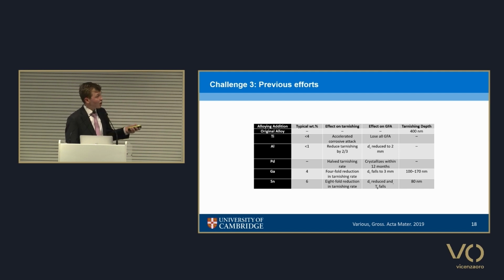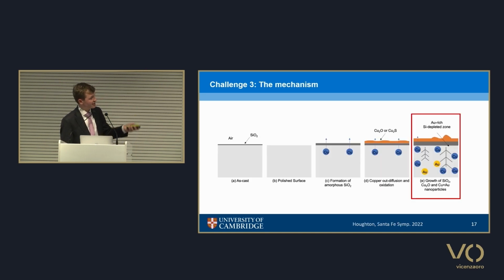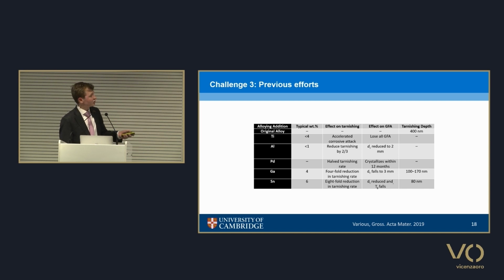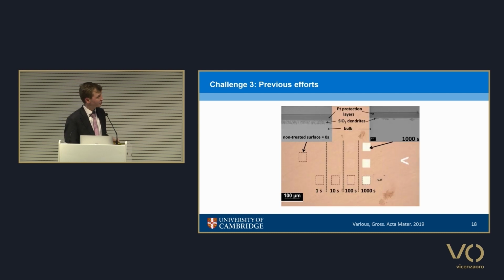People have tried to add other elements in order to try and stop the tarnishing behavior. And in general, we see some improvement in tarnishing behavior. So this is the tarnishing depth of that corrosion scale that I schematically show here. And you'll see some improvement, but ultimately also a drop in our critical casting thickness.